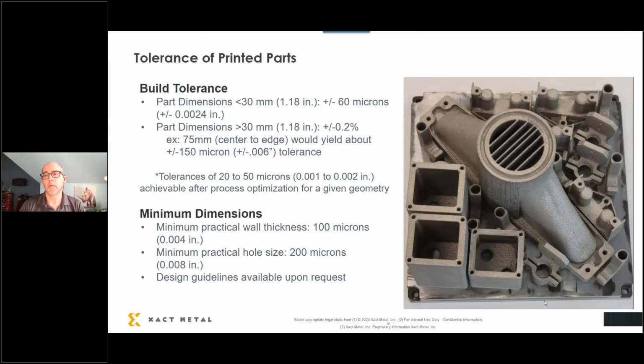Tolerance of printed parts. Everybody's going, hey, what's your tolerance, right? I want to make sure we cover that. So parts that are about 1 inch and 3/16, we can hold about 2 thou tolerance, plus or minus 2 thou over 1 inch and 3/16, or about 30 millimeters. 60 microns over about 30 millimeters. Beyond that, everybody's got this ratio figure. It's a 0.2% tolerance for every 30 millimeters beyond that.